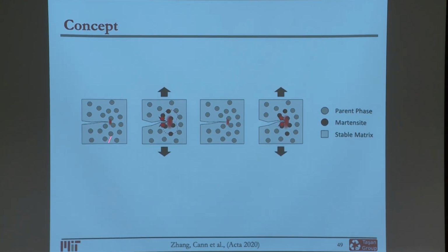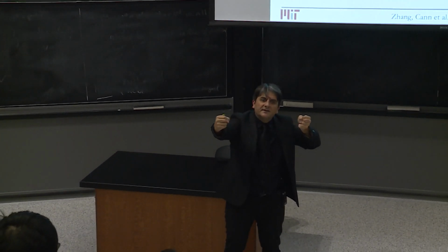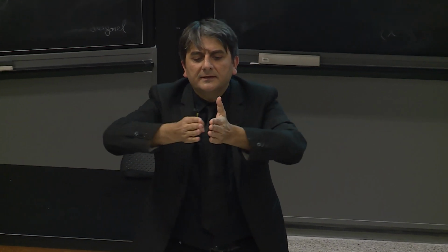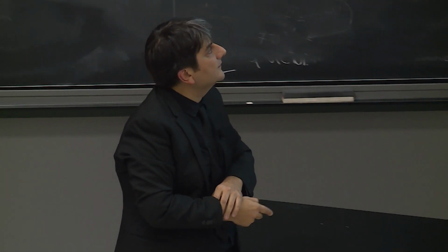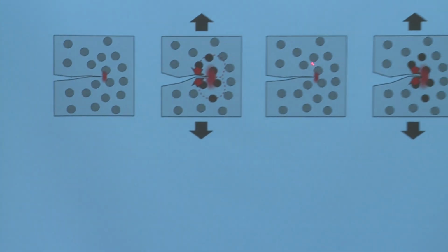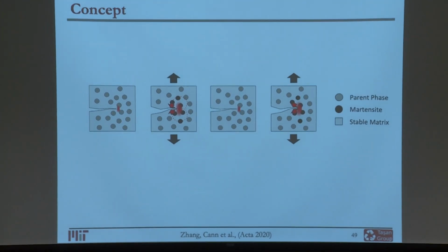So you can imagine that this doesn't really make too much sense in an example of quasi-static loading. So if you are constantly loading a material, this wouldn't take place. But this kind of concept is more for fatigue scenarios, where you have cyclic loads that would create stresses at the crack tip and release of stresses upon tension and, for instance, compression cycles. So when you have stress, then you have the forward transformation. When you have downtime, you have sort of the reverse transformation taking place.